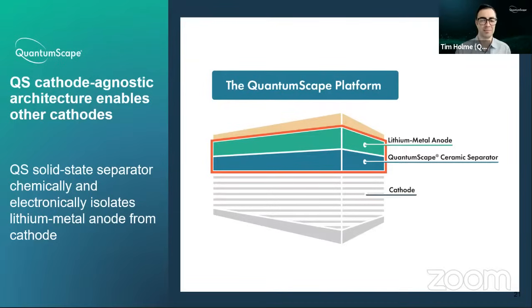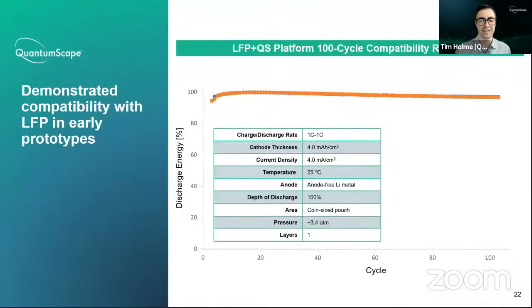By developing a ceramic separator that separates the anode from the cathode, you can then anticipate using different cathode materials because you have isolated the anode from the cathode electronically and chemically. So we actually have done a little bit of early testing just to show that it could be done at a conceptual level. This is still early testing, but it shows that you can have very minimal capacity degradation over initial cycling in an LFP cathode with a QuantumScape cell. So the rest of these test conditions are listed here. I won't go into every one of them, aside to say that this was an early test result done in small size cells, but it does illustrate the principle here that you can get compatibility.